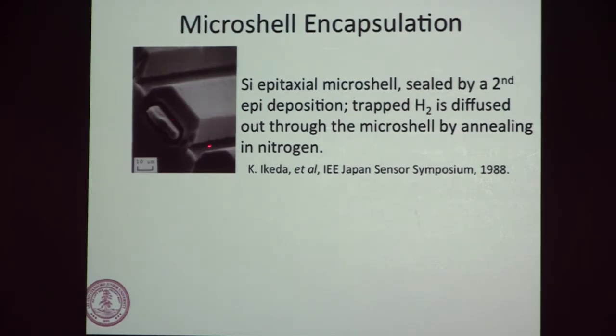This was built with etch access holes to micromachine out all of the oxide, and then they deposited this epi layer and sealed up all the holes. Hydrogen was sealed up with it because in an epi reactor, there's basically a hurricane of hydrogen going through to create the right conditions for epitaxial silicon growth. How do you get the hydrogen out? You heat it up in a nitrogen furnace, which you have in your nano center, and the hydrogen goes out and the nitrogen can't get through, and you end up pumping a vacuum and having a very tightly controlled environment.